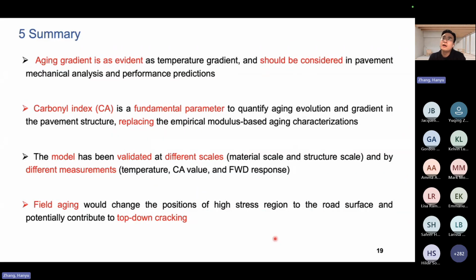I think maybe more than 20 years ago, when we developed the global aging system, developed by Professor Witczak, we used viscosity. Then in one of the NCHRP projects led by NC State University, we used modulus. Now in our project, we decided to use carbonyl index because it's a fundamental property of the mainstream binders.